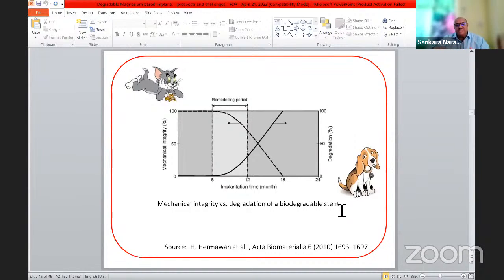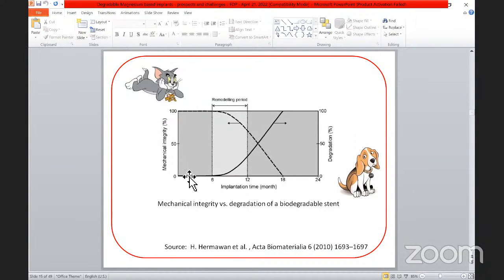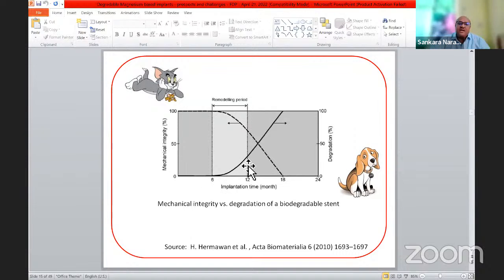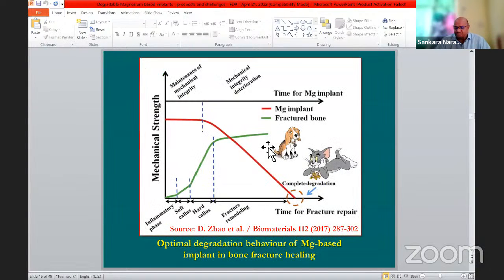Okay, normally we have to establish, as a function of time, that you need to maintain mechanical integrity up to this stage. Beyond the stage, you should be able to degrade much faster. So you should be able to hold for about 15 months. Then after that, it should degrade. But what happens is it is degrading much faster, and the mechanical integrity is becoming very poor. So that's why we have the problem of developing magnesium.